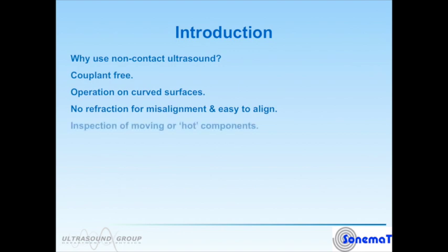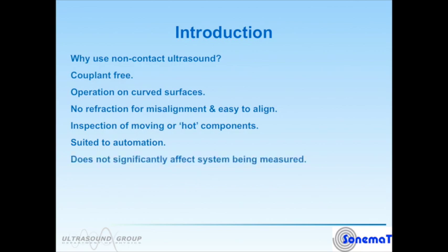Having a non-contact transducer makes it much easier to inspect moving or hot components. EMATs can be water-cooled and have been operated to temperatures of over 1000 degrees centigrade. Combining all these features together means that EMATs are highly suited to automation or robotic inspection. Also, because an EMAT is not actually physically touching the system in many cases, it doesn't significantly affect the measurement that's being made.